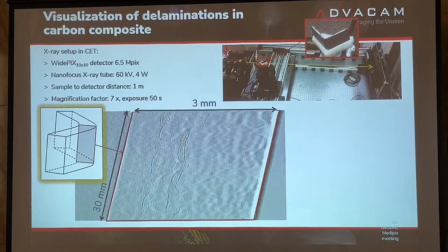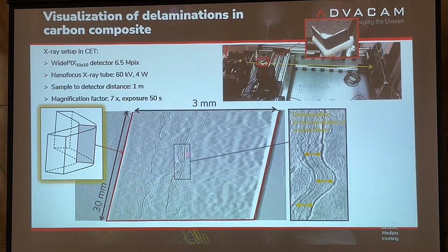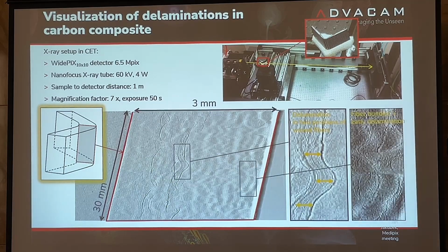So we performed the measurement, and really you see them nicely. So these are the delaminated layers of the laminate. Here the aspect ratio is very stretched in this direction. So this is 3 millimeters, while this is 30 millimeters. So it's just for display. So you start to see various features there.